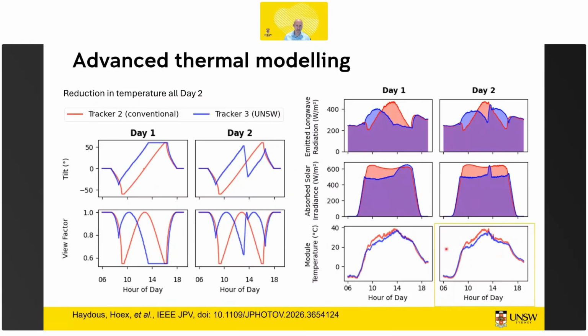And we saw that if you control your curtailment or clipping by the tracker, you can actually run your modules even up to 10 degrees cooler, which of course reduces degradation, but also the UV. Of course, if you're not following the sun, you would see less UV. So that's another way to reduce degradation.